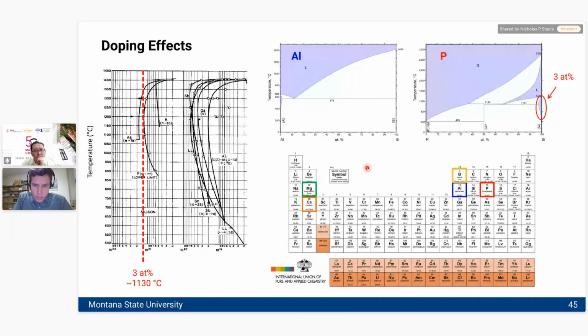So we decided to try and see what would happen when we dope silicon with a substitutional dopant. What would that change in terms of the lithiation and delithiation properties of that material? We chose phosphorus as our first dopant of interest because it has a massive solubility in silicon. You can actually get 3 atomic percent phosphorus into silicon at equilibrium. And so for that reason, we're going to look at the phosphorus results first today.